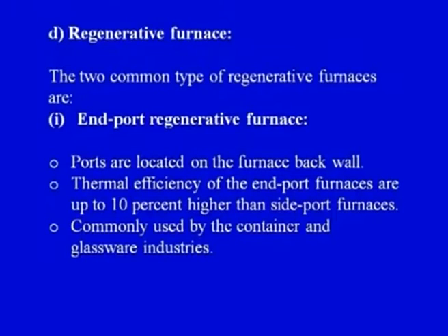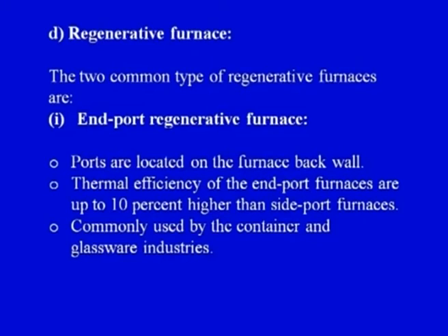Finally, we have the regenerative furnace. The two common types of regenerative furnaces are the end port regenerative furnace and the side port regenerative furnace, which we are going to see in the subsequent slides. In case of end port regenerative furnace, ports are located on the furnace back wall. End ports are at the furnace back wall. Thermal efficiency of end port furnaces is up to 10% higher than the side port furnaces.